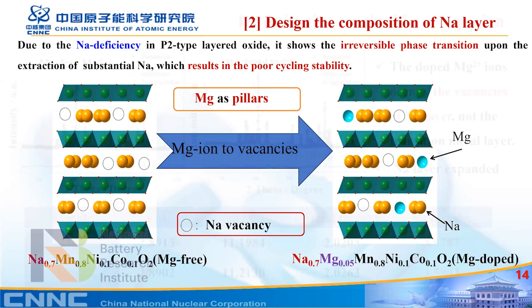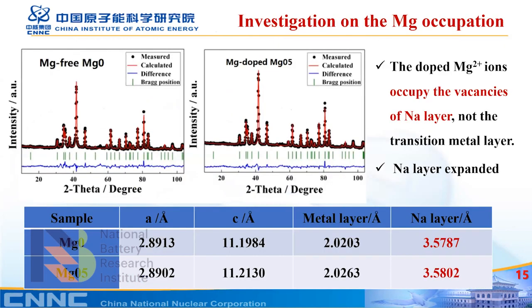Let's see this slide. Now we use the CARR high intensity neutron diffractometer. We also call this diffractometer the Peking University diffractometer, because we co-built this diffractometer. It is quite productive per year. It can measure more than 300 to 500 samples. So now we use this Peking University diffractometer to study the location of the magnesium ions. And we found that the doped magnesium ions occupy the vacancies of the sodium layer, not the transition metal layer. And most of the magnesium enters the vacancies of H-shared sodium sites rather than the face-shared sodium sites. This may be due to the much higher stability of the H-shared sodium site than the face-shared sodium site.